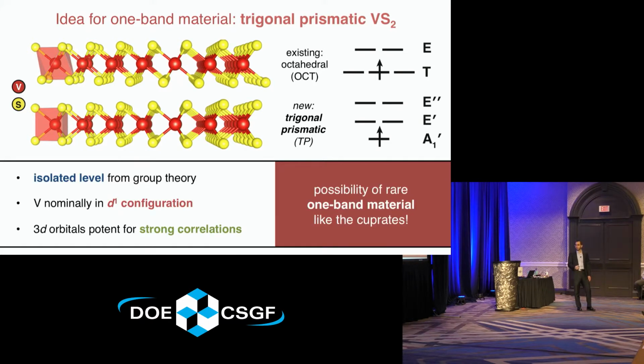Now, we choose vanadium disulfide not only because it'll have, in principle, that isolated level from group theory, but also vanadium would nominally be in a d1 configuration. So that's exactly what I'm looking for. In addition, by choosing vanadium, those are 3d orbitals. Those tend to be the most localized, so the most susceptible to this strong correlation physics. So this could open up, in principle, the possibility of this rare one-band correlated material in analogy to the cuprates.